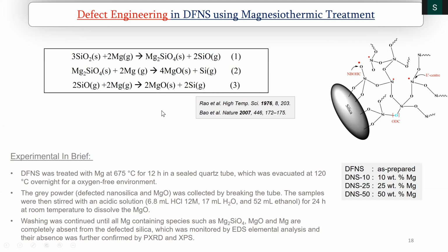We thought this can be selectively used. Rao et al., and then there is a follow-up paper in Nature, Bao et al., where they converted SiO2 to Si using this magnesiothermic treatment. We said, let us stop at reaction step 1 by tuning the magnesium concentration and reaction time. By tuning that, we could tune the number of Si radicals and O radicals, and that may give us a catalyst. So we tuned the weight of magnesium, 10 weight percent, 25 and 50, and prepared a range of these defected DFNS.